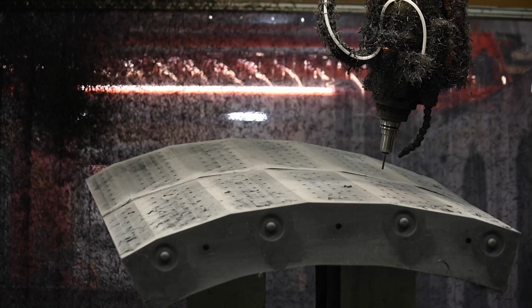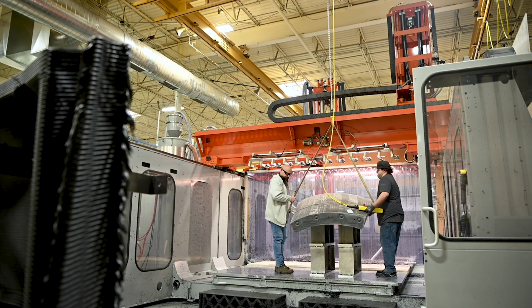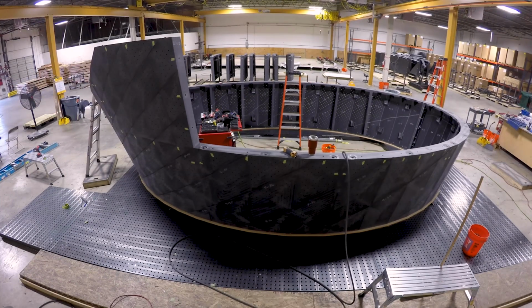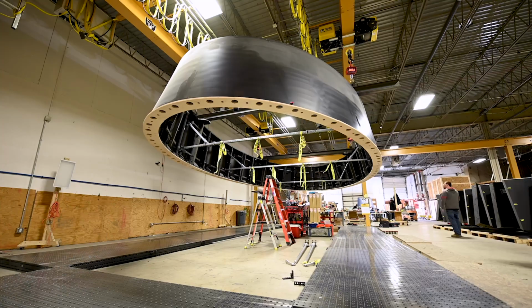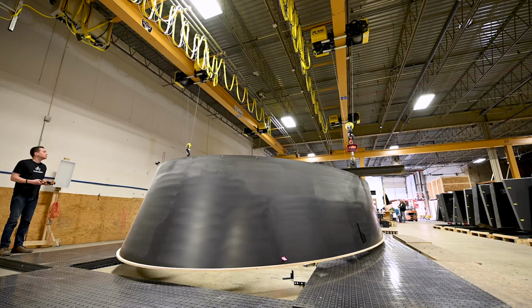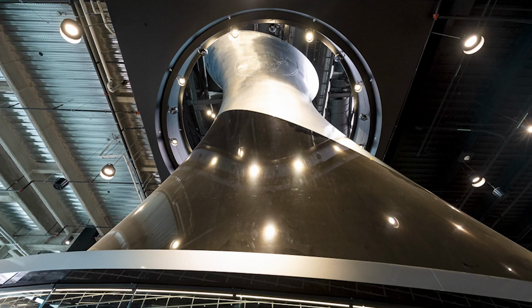Reportedly, it took 50,000 man-hours in total to design, manufacture, and erect the impressive additively manufactured structure. The 3D printed torch consists of as many as 225 additively manufactured blocks, with each one weighing approximately 350 pounds. The blocks were 3D printed on a large format Thermwood LSAM machine that Dimensional Innovations acquired from Thermwood in 2019. The company chose carbon fiber reinforced polycarbonate composite for this project, and more than 100,000 pounds of this raw material were required to fabricate all of the blocks.